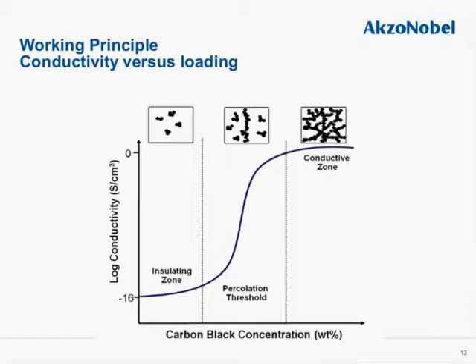And we reach the full conductive zone, which is the third zone in the graph, when a vast majority of those carbon black networks are in direct contact or close enough that they can ensure full conductivity over a three-dimensional network in the conductive zone. I will have a few slides in the follow-up where I indicate some concentrations, but in general, the polymer network, the type of polymer, the morphology of the polymer, the type of other additives present in the end compound, as well as processing conditions and temperature are all playing an important role in achieving full conductivity of the product.